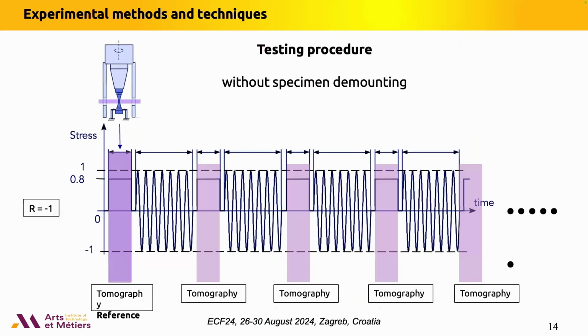So the methodology for testing is the following. At the beginning, when the specimen is a virgin without any cyclic loading, we do tomography. It gives a reference state of the material and of the defects of the microstructure. And this scan is done at a load level corresponding to 80% of the stress level that you want to be applied during the testing procedure.